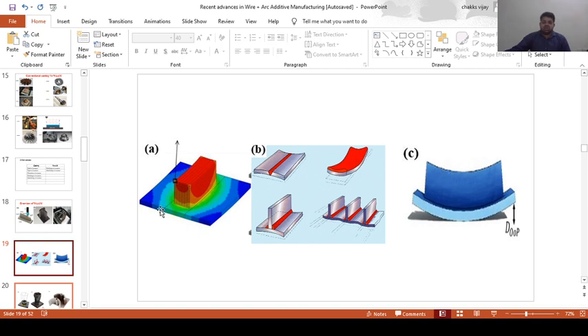So we have to choose a base plate which is slightly thick, and I already told you that if we are going to deposit stainless steel 316L, the same material should be chosen as the base plate. We cannot choose aluminium or some other irrelevant material as a base plate. The same material should be used so that we can avoid chemical contamination.